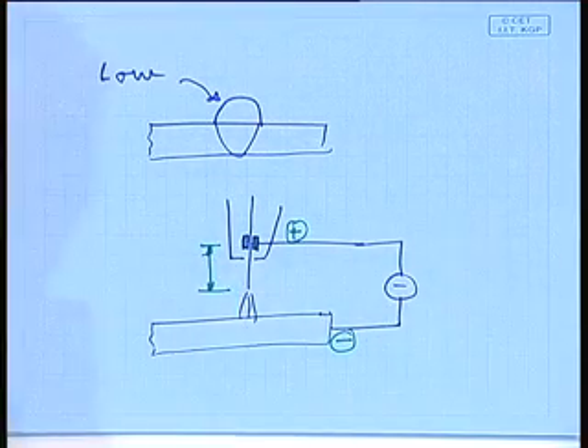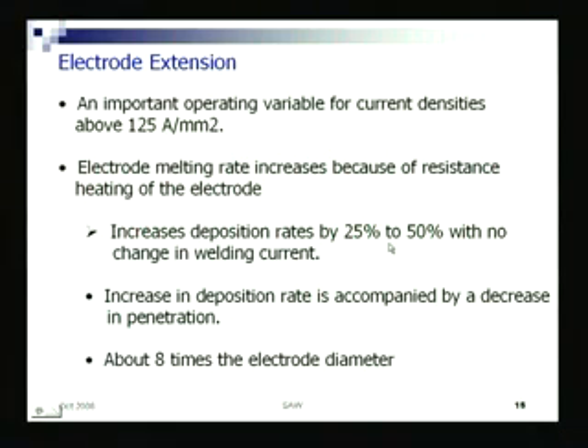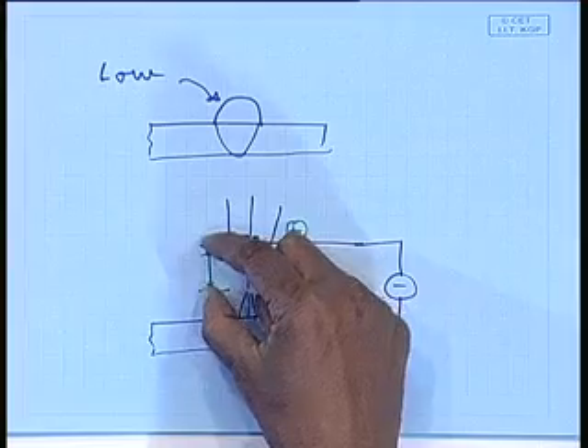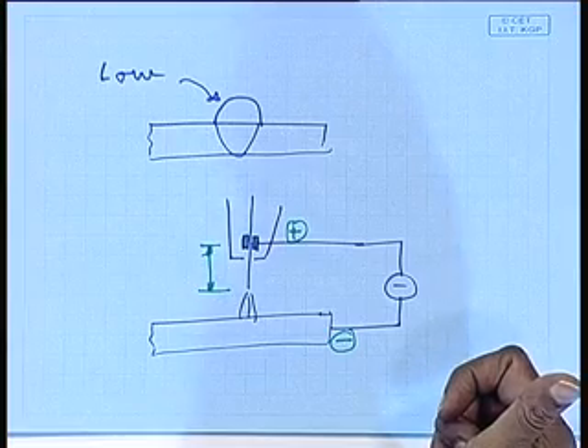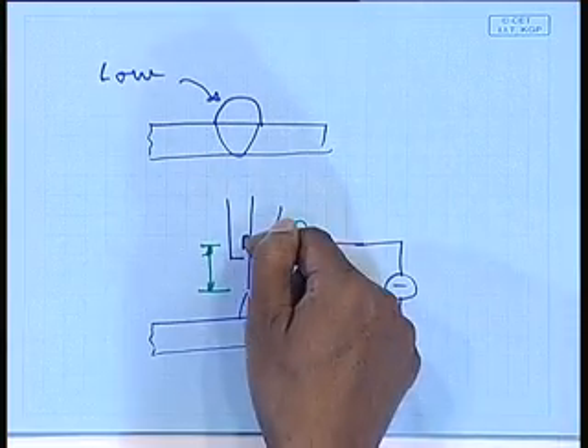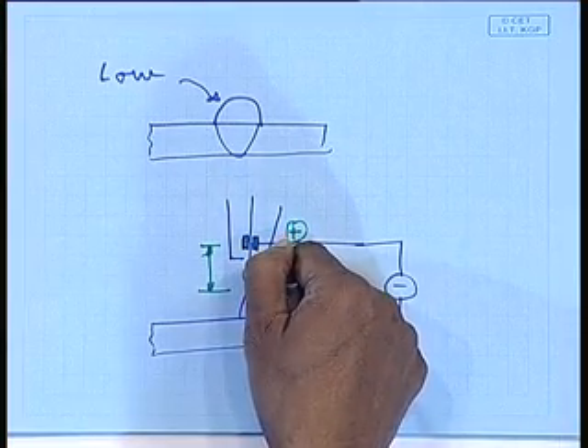So if the electrode extension is high, it results in a higher deposition rate. With all other parameters remaining constant, if I just increase the electrode extension, my deposition rate increases, because of the additional joule heating.